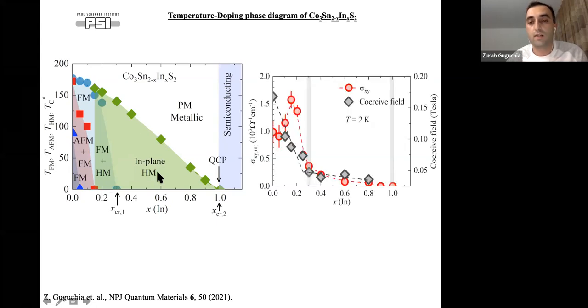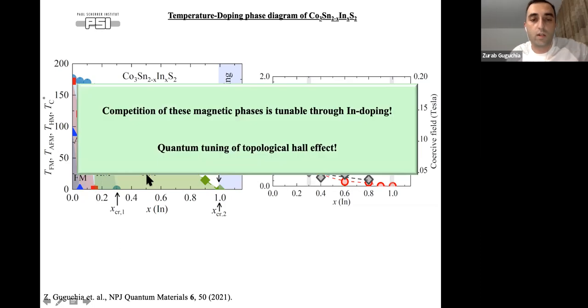At the same time, if you look at this intrinsic Hall conductivity, you see that in this in-plane state, the Hall conductivity is nearly 0, and we get some kind of non-monotonous behavior within the state where we have a mixture of phases. So we can control the Hall conductivity by tuning this competition and by moving the system into this helimagnetic state. This we call a quantum tuning of the topological Hall effect.